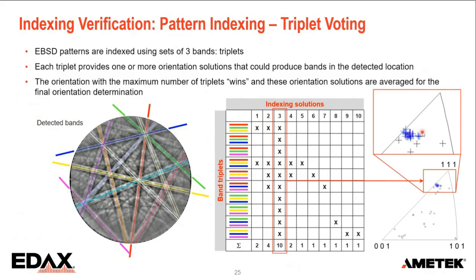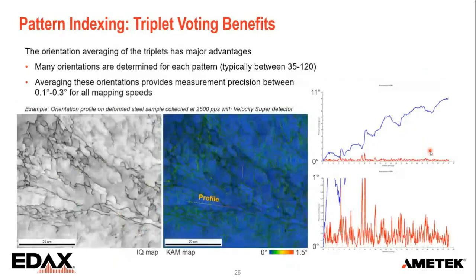Then the cloud just gets bigger, but the average stays in that point. To illustrate that, this is a piece of the deformed steel that I just showed. I make a profile through one of the grains with some substructure. You can see here that the point-to-point orientation changes are typically well below 0.2 degrees, with some spikes over that, and those are really the low angle boundaries. So the orientation precision that we measure here at about 2500 points per second is between 0.1 and maybe 0.3 degrees. And that really follows out of this triplet voting.